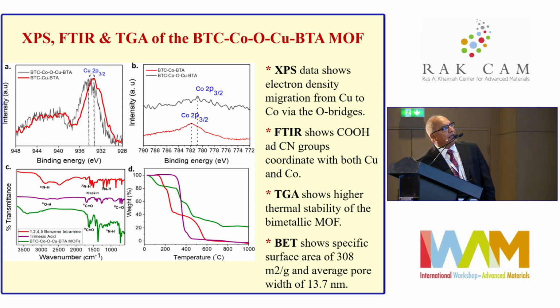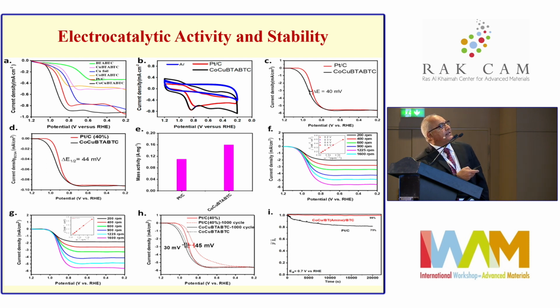Now, in the electrocatalytic activity, we're showing here the current density generated as a function of potential versus RHE, the standard electrode potential for hydrogen. And you can see that the black one is the bimetallic copper-cobalt MOF. It actually has the highest current density profile, the black. The next is the red, the platinum on carbon, and then the individuals: copper foil, the blue, and the green is basically the 2 linkers, BTA and BTC, and the yellow here is the cobalt individual, or the cobalt monometallic MOF. So it's clear that the bimetallic exceeds the current density that can be achieved by the platinum carbon.